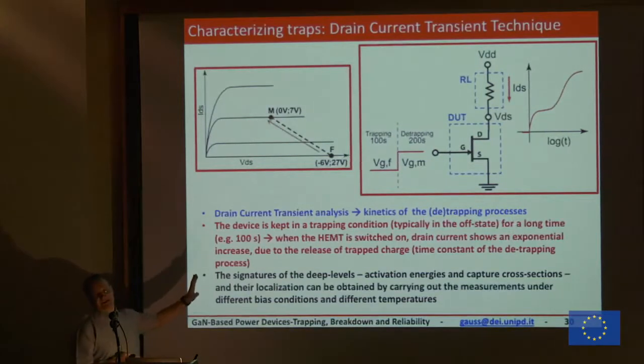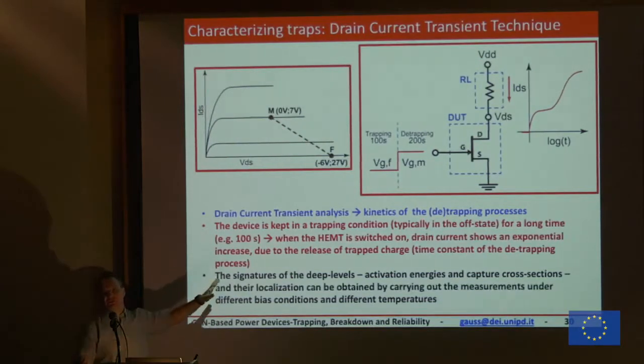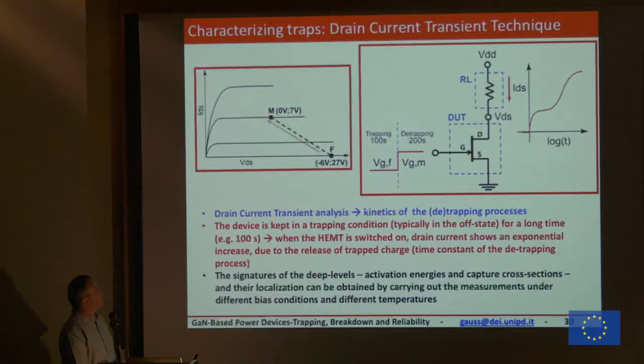So this is not a technique good for qualification of a process. It is a technique used for the developing of the device. And this is what we have done. So let's say that you pulse your device from this typical point, a negative VGS, high VDS, and then you pulse to what you call the measurement point, from this to this. And during this pulse, you don't just measure what happens here, but you are measuring all the evolution of the current, okay?